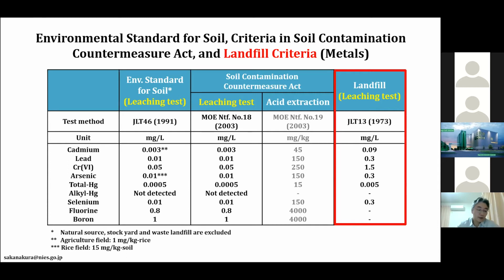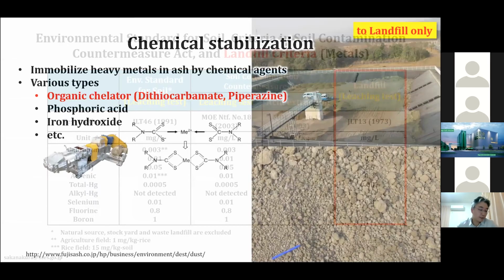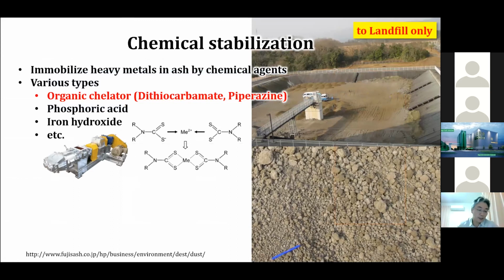So treatment technologies for landfill have focused on reducing the leaching amount of lead and the high pH condition of fly ash. Chemical stabilization is the main treatment technology applied to fly ash before landfill. Heavy metals in fly ash are immobilized by chemical agents such as organic chelators, dithiocarbamate, and piperazine, as shown in the figure. And phosphoric acid, iron hydroxide, and so on are also applied.